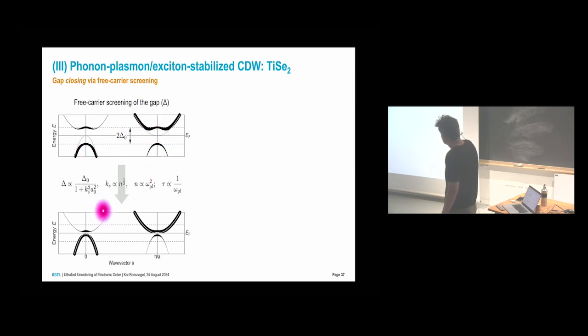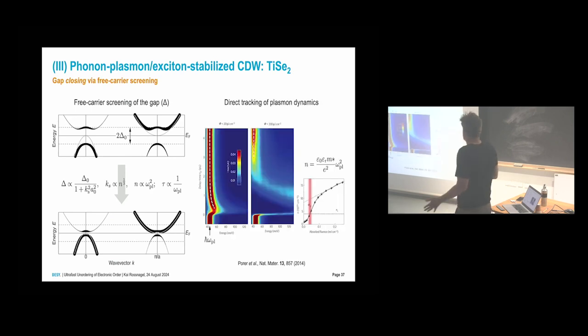So you go from here to here, and you go in a way coherently because you screen everywhere in your material. And this is the experiment where, with Robert Huber, they've directly seen these plasmon-type excitations. So this is a free carrier plasmon at 45 millielectron volts. If you do the hot electron excitation, you shift the plasmon energy to the right. If you do strong excitation, far to the right, and so you have a direct measure via the plasmon frequency of your charge carrier density that does the screening.